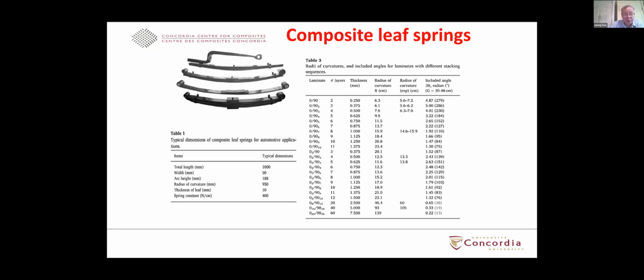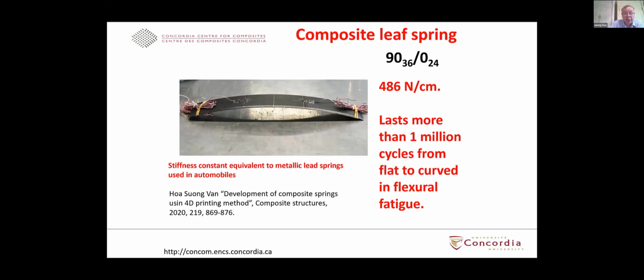But by using the technique of 4D printing of composite, we don't use a curved mold. We use only a flat mold, and we play mainly with the layup sequence. The layup sequence that we use here is 36 layers of 90 degrees and 24 layers of 0 degree. By the time we finish curing and cooling, it gives you this shape. This structure has an elastic constant of 486 Newton per centimeter. That means if you apply the load here, the ratio between the load and the deformation is 486 Newton per centimeter. This number is comparable to the springs that are commercially available right now.